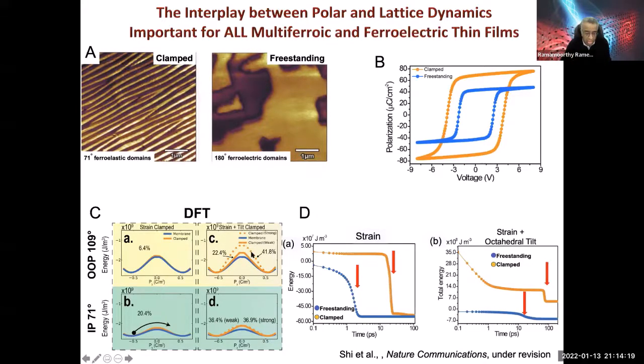And you can see this dotted yellow line. That's when it's completely clamped for both the strain, the lattice deformation, as well as the octahedral tilts. And if you release them from the substrate, the blue is a released sample, that barrier can be about 42% smaller. The phase field calculations show exactly the same, but the difference in energy is about 60%. This is important because it's telling you that there could be big differences in the coercive voltage depending on mechanics playing a role.